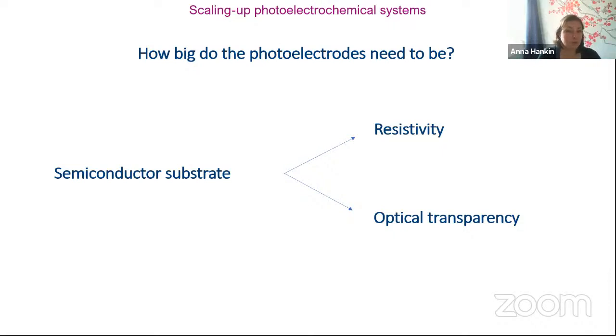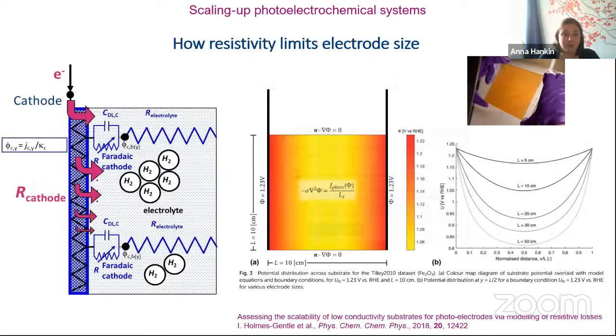Now, when you have small electrodes, these losses are negligible, because you have only a small piece of this oxide and because you don't have a lot of current going through it. And the argument was that, well, photoelectrochemical systems, they don't operate at thousands of amps per square meter, like electrolyzers. So you're not gonna have much resistance, even in resistive materials, but that's absolutely not true, because charge always follows the path of least resistance. So these effects are going to become apparent very quickly. So you've got this issue of resistivity versus optical transparency, right? The more optical transparency you have, the more resistivity you have. And this has been proved